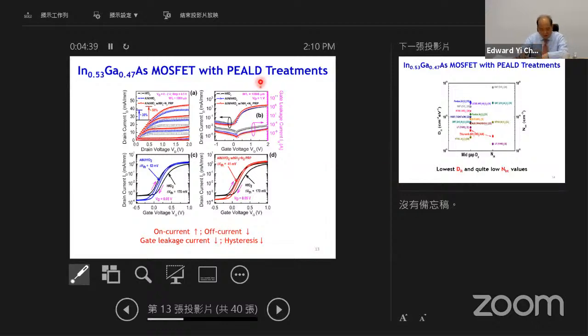And after that, we also do plasma treatment. Okay, the device is done, and then we do post plasma treatment. And in this one, you can see that we compare just hafnium oxide, which is the white line, and again with aluminum nitride interface, which is the blue line, and finally with the remote ammonia gas treatment, which is the red line. You can see there's an increase of 58% of the current after treatment, because the surface is greatly improved, so your mobility is improved, okay. And then you can see that the off current is also reduced, because the defects are reduced, and the hysteresis is decreased. So overall, you increase the on current, which makes your device move faster, and you have low off current, which is energy saving, and you reduce the hysteresis, so your BTS is more stable. Okay.